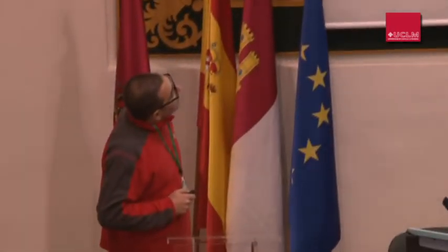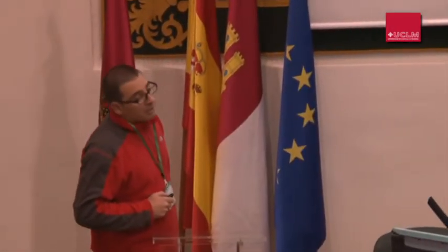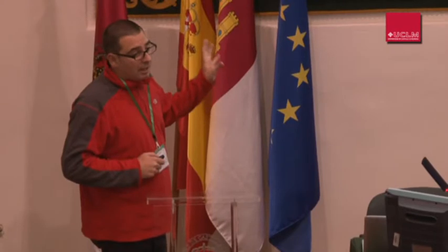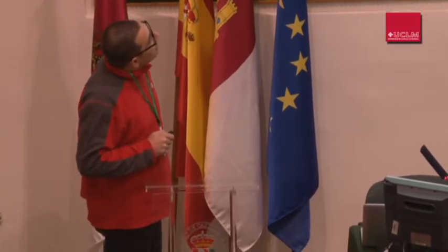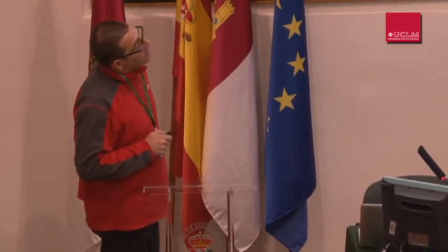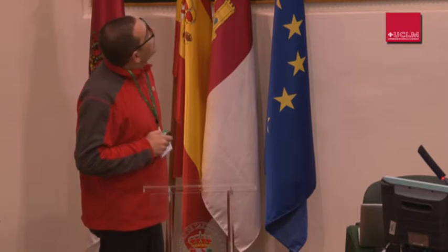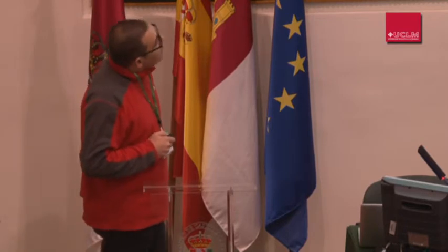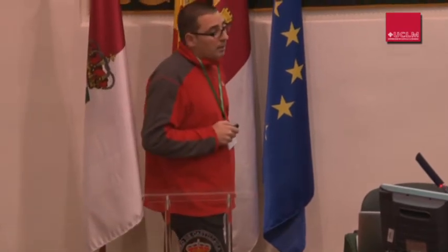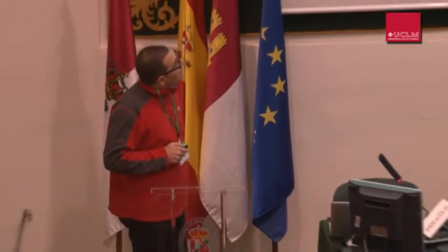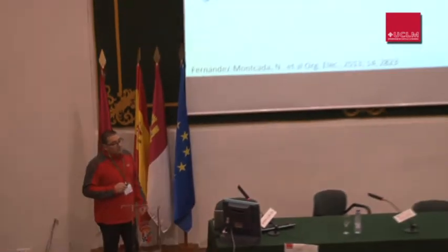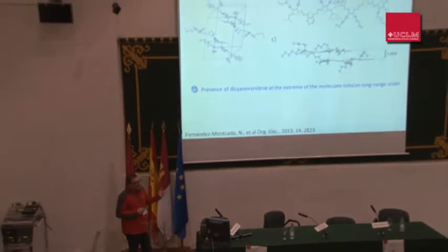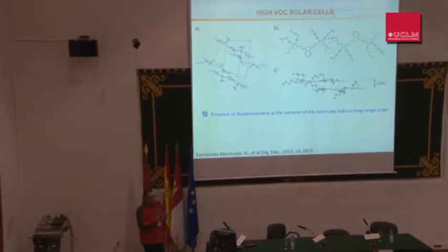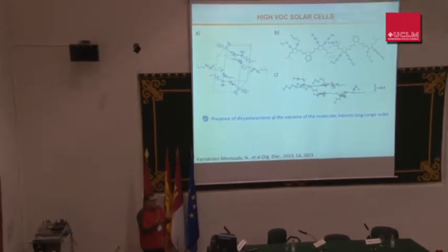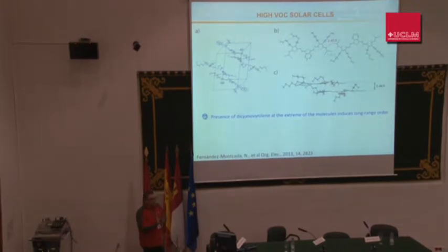The fill factor in small molecules is usually very bad. In this case, it was very good, above 60%. The problem is the current. You only get 6 milliamps. The reason why these molecules work so well was very surprising. Most of the bibliography before this paper claimed that you need to have pi-pi stacking, because they have aromatic units and people are keen on pi-pi stacking.